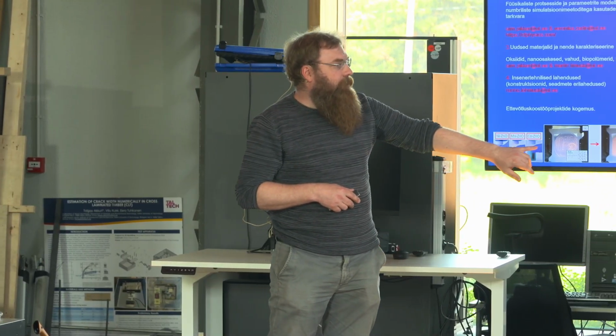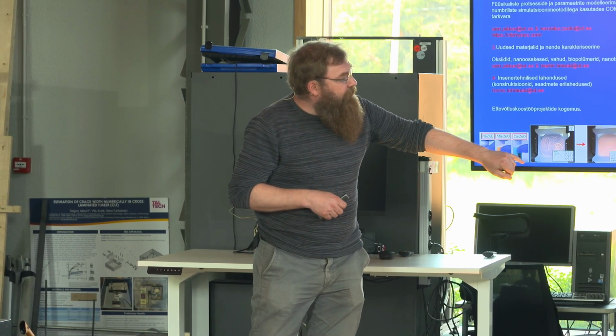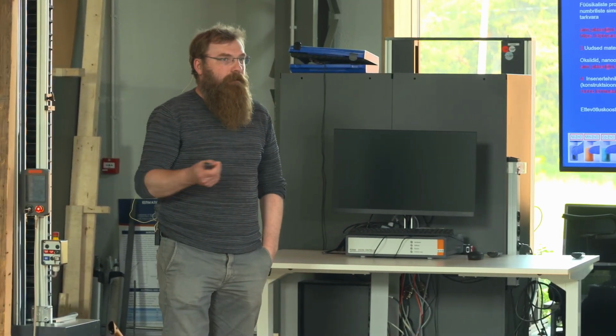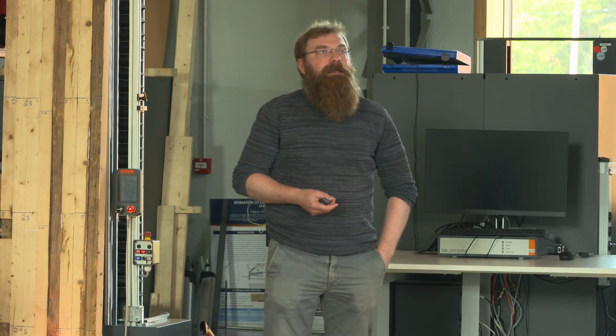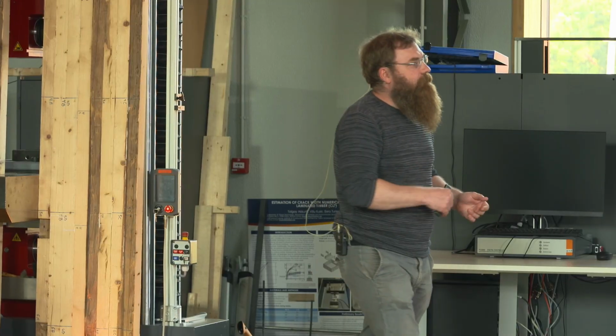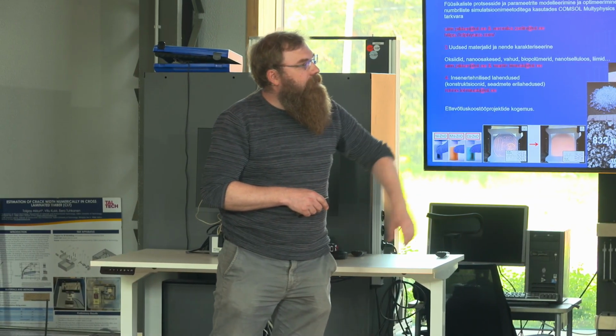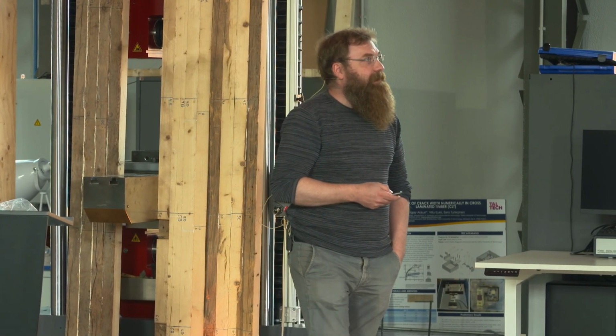So we have then also developed, Martin mostly here, transparent glass which can be switched thanks to electricity from transparent to opaque, and that with a novel solution which was a spray coating method. So it was kind of a cheap method, but in the practical sense not viable, because it is a self-organization effect that happens there. It's very sensitive to humidity, temperature, vibrations, and so on. So in that sense, it was not practically viable. So a lot of research has been done on metal oxide foams, aerogels, stuff like that. So there is a history of, let's say, material research.